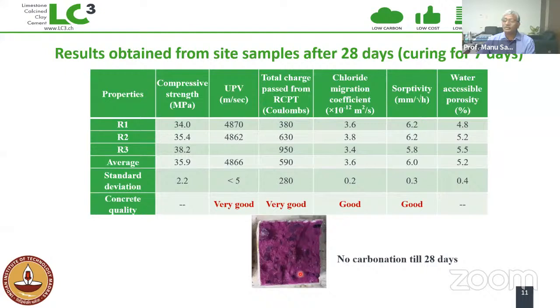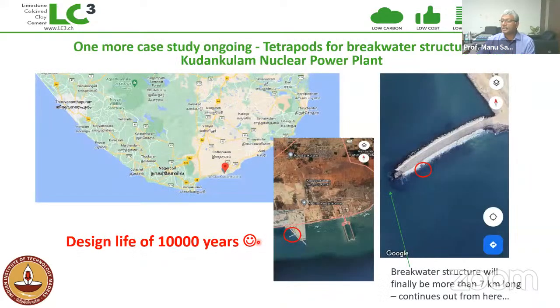And in the very early stages, we also did not get any carbonation in these specimens. Now, there's another site where we actually used LC3, and this is a very different site. It's actually a highly controlled concrete manufacturing site where they're using concrete to manufacture tetrapods to make this breakwater structure. The breakwater structure is going to be nearly 7 kilometers long.